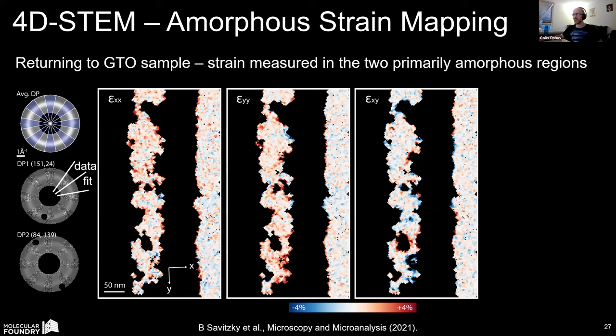Very interestingly, if you look at the strain fields in the mixed region, you can actually see the sort of red and blue, especially red though, banding around a lot of those holes. Those are where large polycrystalline grains nucleated. And because they have a different atomic density from the amorphous phase, they pull on the local atomic spacing in the amorphous region and change the local atomic spacing, which we can measure with this method.